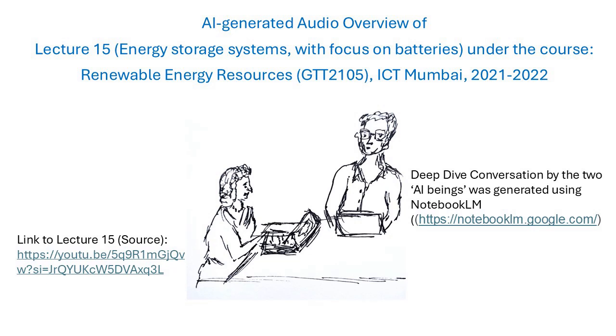Precisely. Professor Ghosh notes the cobalt in LiCoO2 changes oxidation state from Co3+ to Co4+ as it gives up lithium ions during charge. He shows a nice simple diagram, right? Ions just shuttling back and forth like a rocking chair. Yeah, the rocking chair battery. And the voltage comes from the difference in energy levels, the chemical potential for lithium in the anode versus the cathode. And the electrolyte is key for that shuttling. Non-aqueous solvent plus a lithium salt dissolved in it, like LiPF6, to carry the ions. It's the medium for that ion dance.